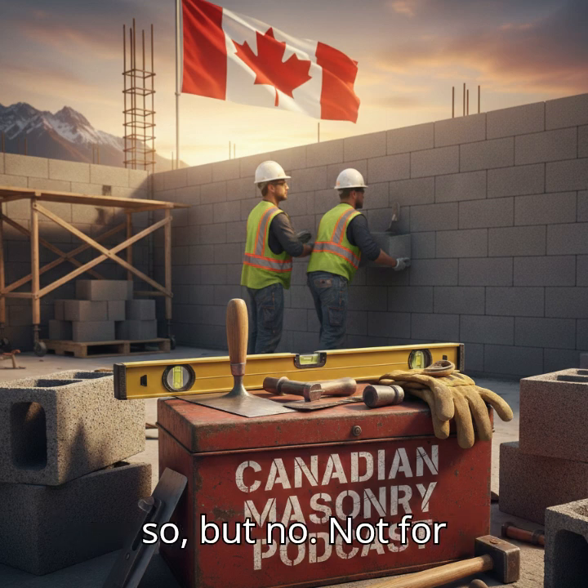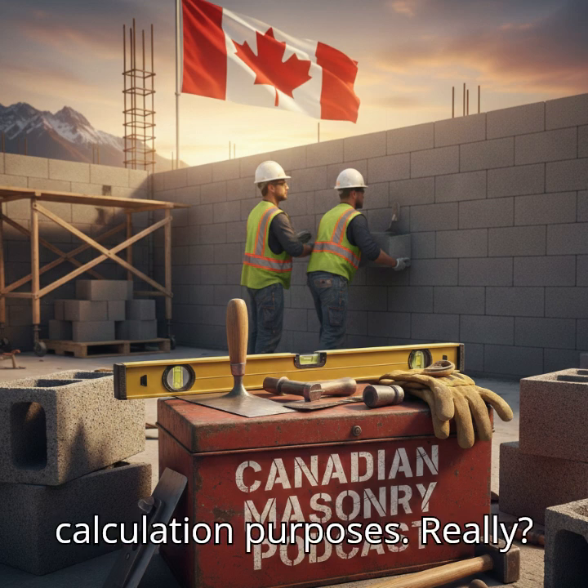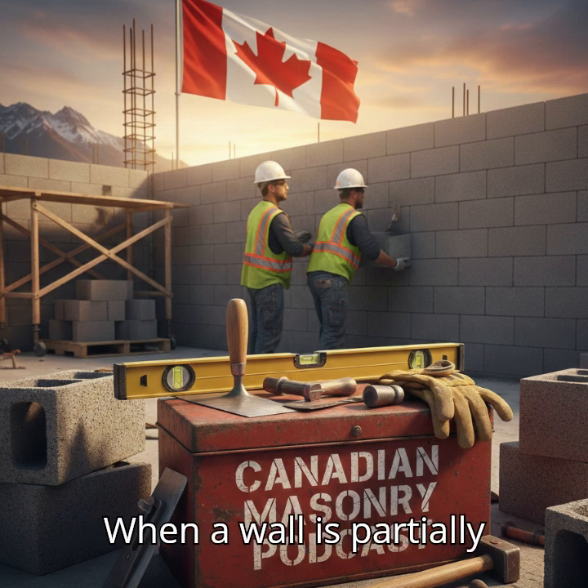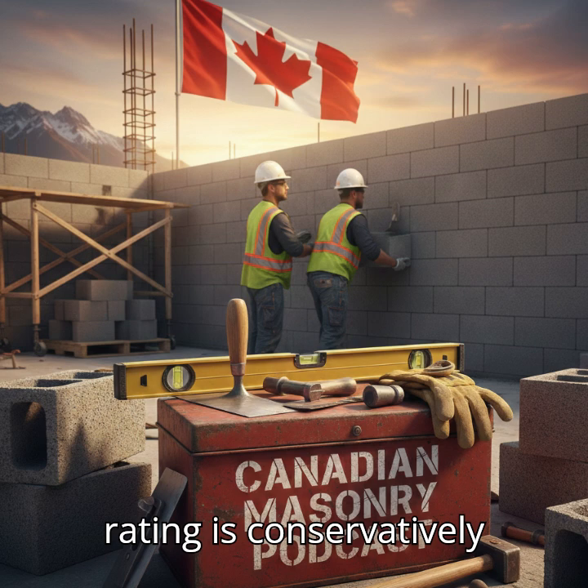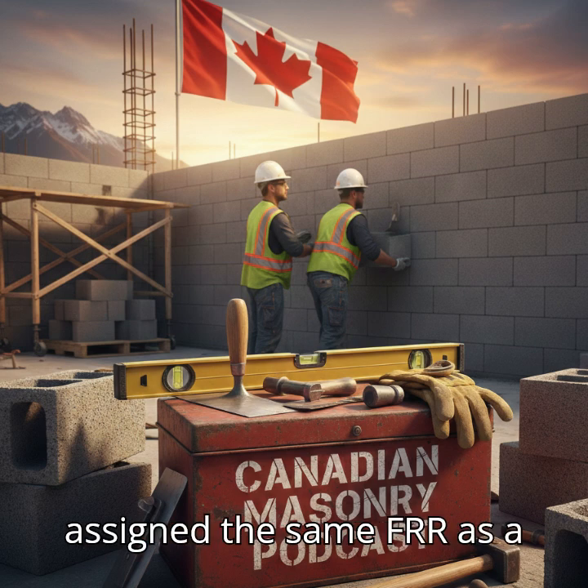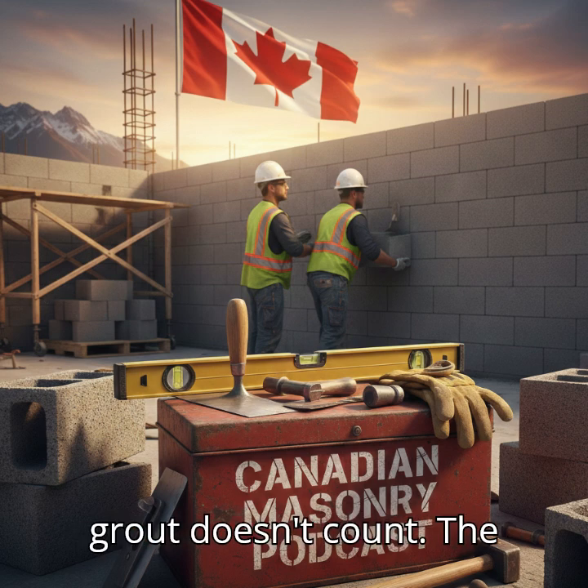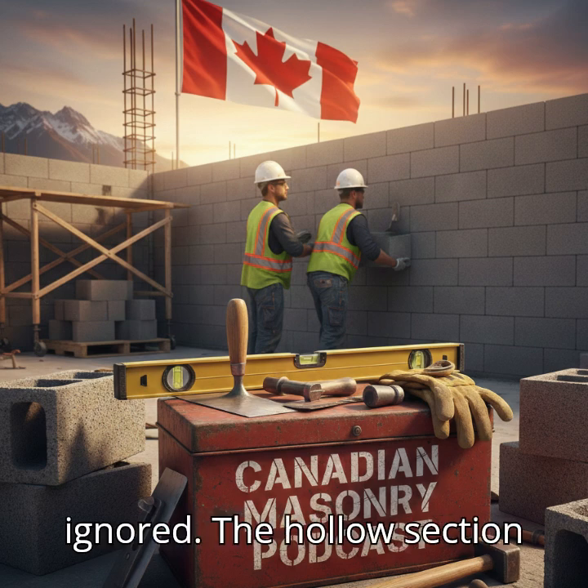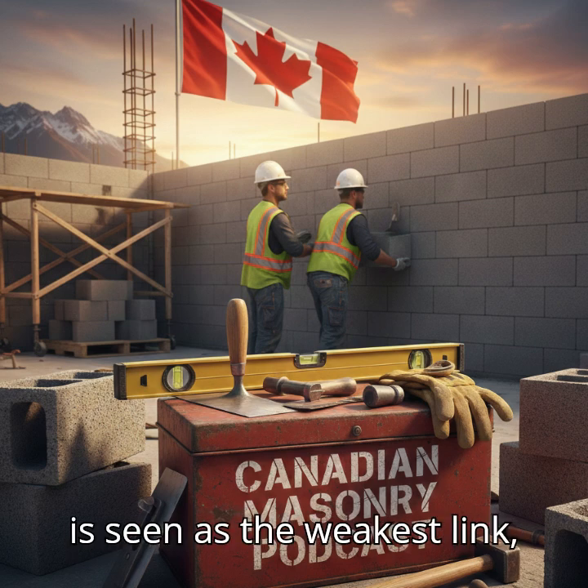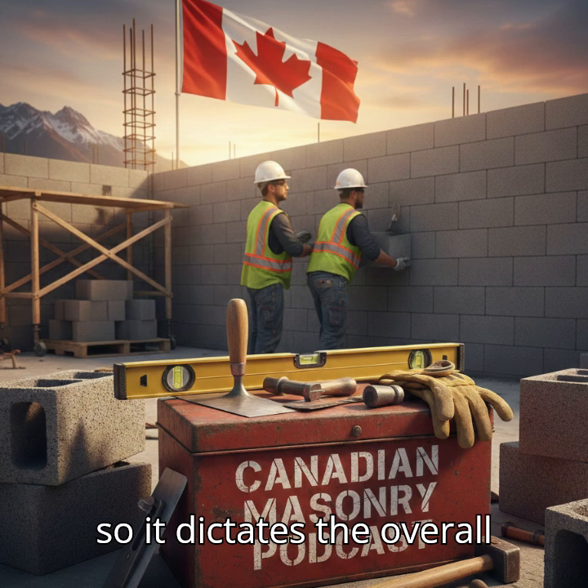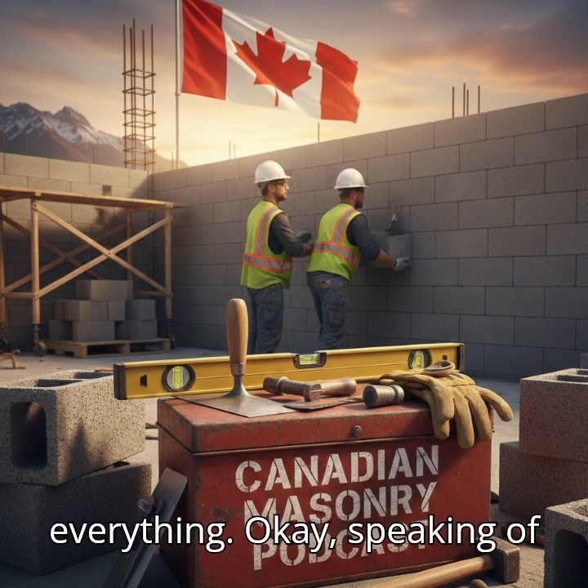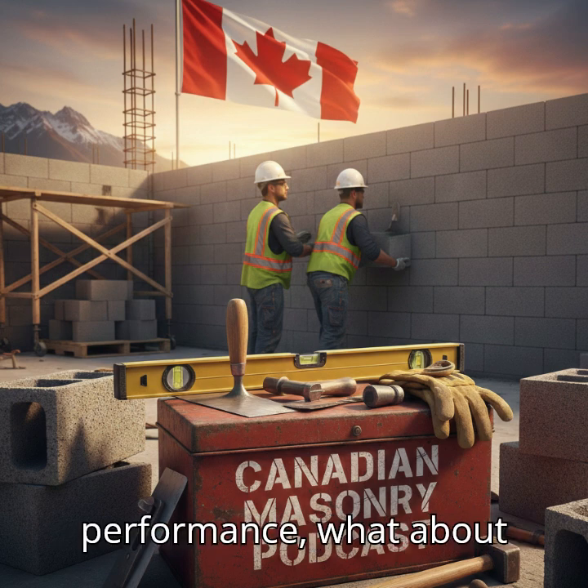You'd think so, but no. Not for calculation purposes. Really? When a wall is partially grouted, say for some vertical rebar, the fire rating is conservatively assigned the same FRR as a fully hollow wall. So the grout doesn't count? The contribution of the grout is ignored. The hollow section is seen as the weakest link, so it dictates the overall rating. Continuity is everything. Okay, speaking of performance, what about sound?